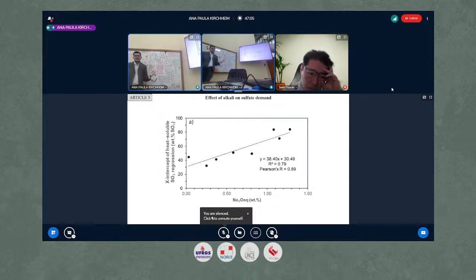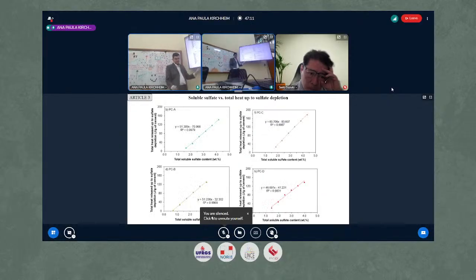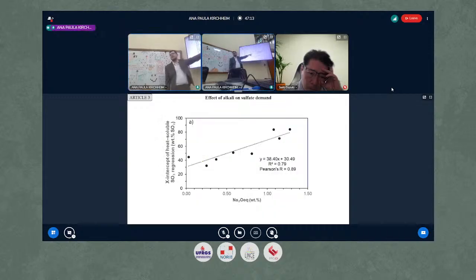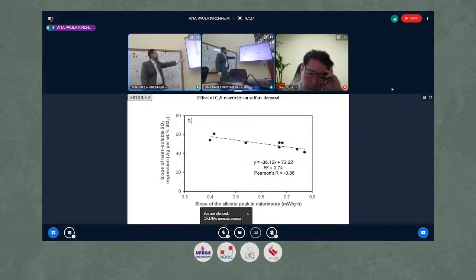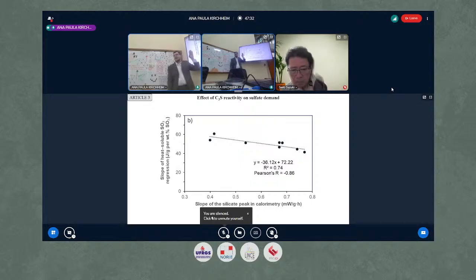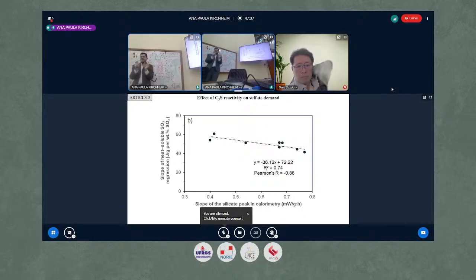And when we evaluated the relation between the X intercept and the alkali, we see a good linear relation, and now we don't need to exclude PCG from this regression. All of them agree well. But PCG can be explained by the slope of the silicate peak. That correlates very well with the slope of the regression. So now, putting 2 parameters from this analysis, I can explain all my clinkers. So we have a great influence of alkali content and also from silicate reactivity.